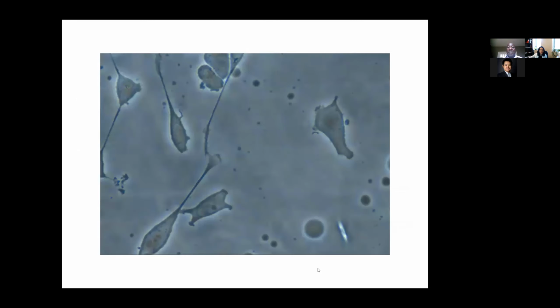And so just to give you an example, I want to start with this video here of a shear assay experiment where we essentially flow liquid over cells that are distributed in a fluidic channel. So although you can't see it, the cells are being displaced. And gradually, as we increase the shear stress by increasing the velocity, you will see that the cells start getting deformed. And in this case also, you see that the cells start getting detached.